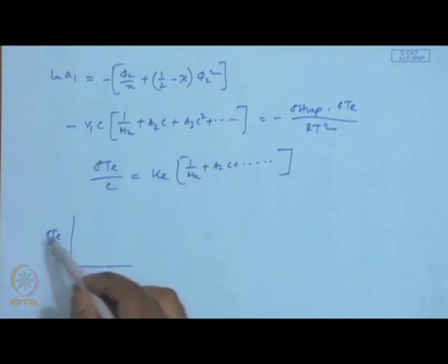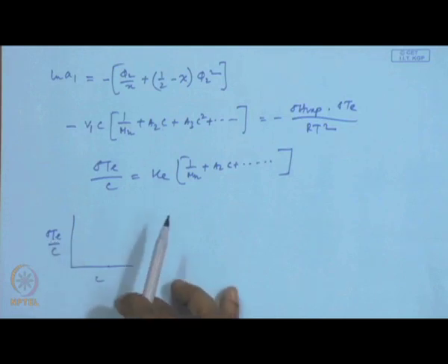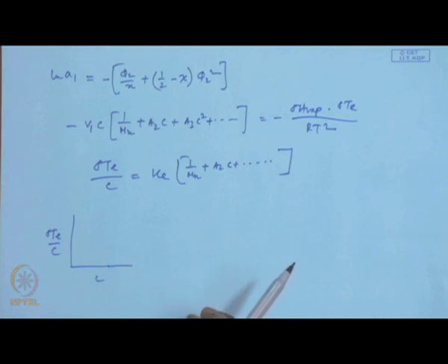In practice, we actually do not reach equilibrium because some of the heat of condensation of the droplets gets dissipated on the thermistor and the solvent stream. So, what we reach is not a true equilibrium, it is a steady state. So, we need to calibrate the experiment with known molecular weight polymer solutions to determine the number average molecular weight for the unknown samples. So, this is not an absolute method, we need calibration.